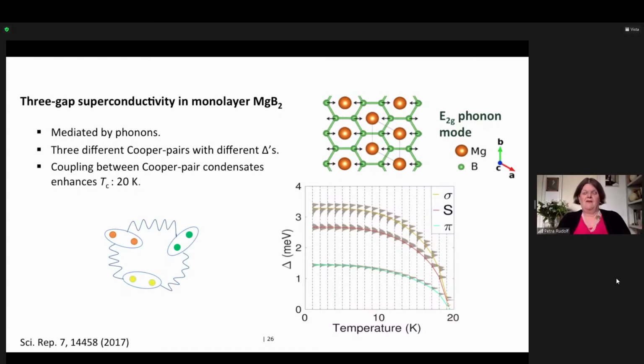Or when you have a very thin layer, of course, the surface electrons are the most important. So what he found is that while in normal bulk magnesium diboride, you have 2 types of Cooper pairs with different gaps, when you have only 1 layer, or when you have surface atoms in a very thin layer, the surface electrons, you actually get 3 types of Cooper pairs. And they are all coupled, and one can get a very different behavior than if one doesn't consider it.